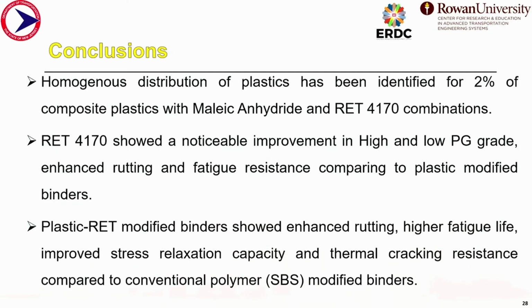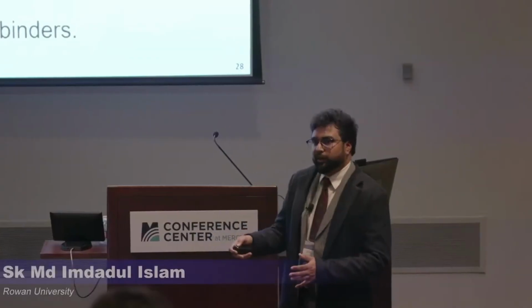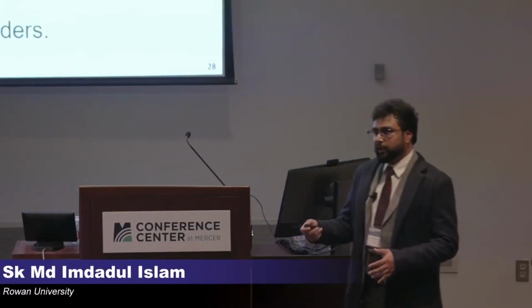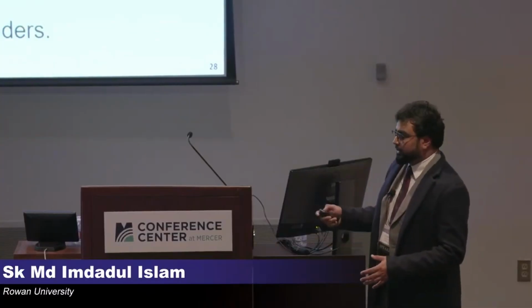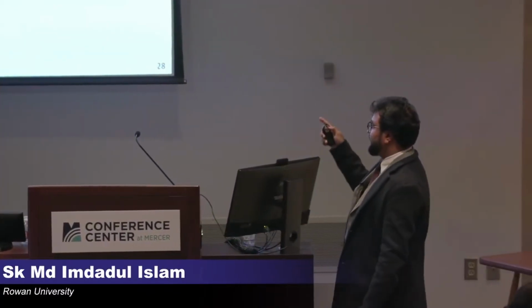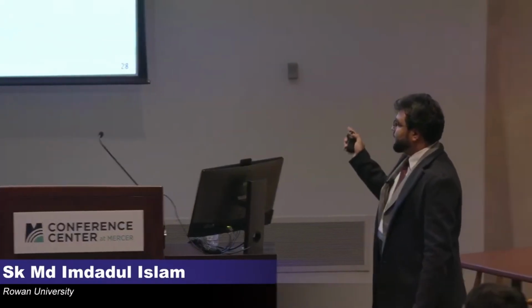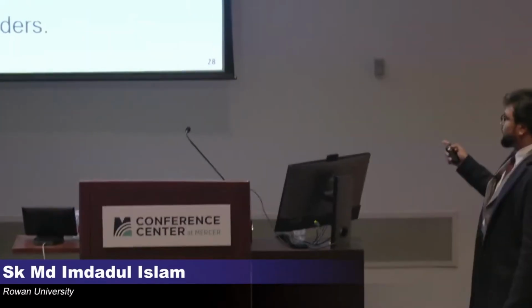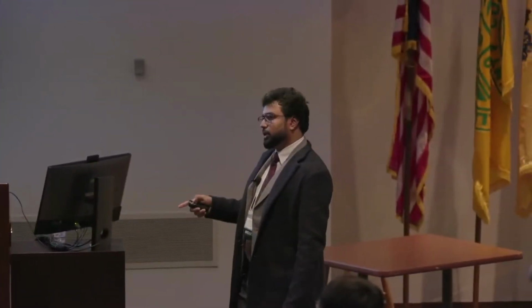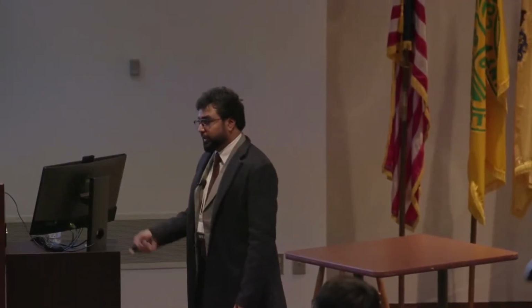And it's worth mentioning that we also did a comparative study of the plastic and RET modified binder with the conventional polymer modified binder that we have in our industry now, which is SBS modified binders. And surprisingly, we found that the plastic RET modified binder showed enhanced rutting, higher fatigue life, improved stress relaxation capacity, and thermal cracking resistance compared to the conventional SBS modified binder that we have now.